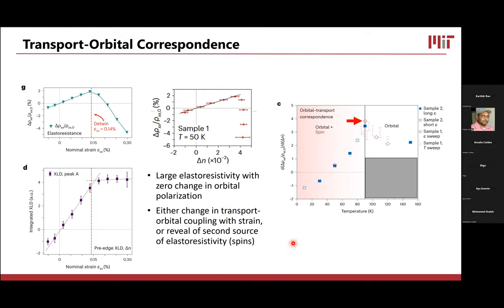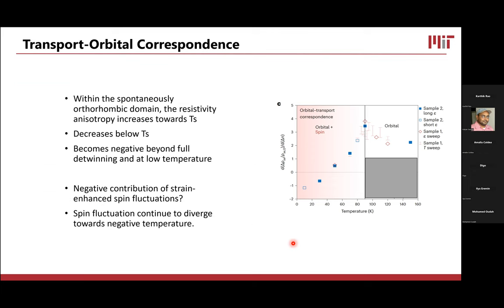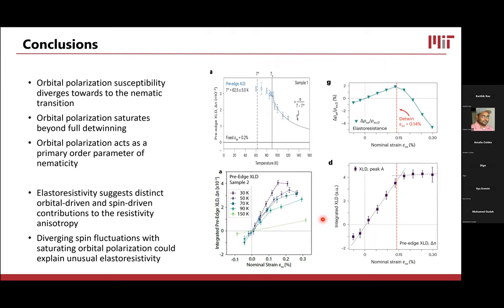And again, I would say that what's happening here is as I make the sample more orthorhombic with increasing strain, I'm promoting spin fluctuations, I get more spin scattering, and I get this extra contribution to the elastoresistivity. It's a relatively simple picture, but I think that it gives an idea for what might be happening here. So I put this all together, and we have at least a picture that we can talk about for why we have a sign change in the elastoresistivity below the nematic transition.